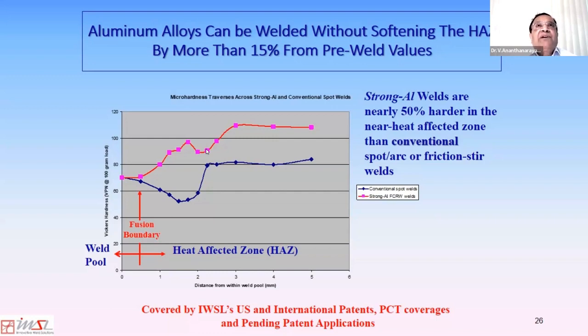And then I would do some cross sections to see how the welding process has progressed at the weld interface, and whether it has pushed out all the dirt and all the asperities in the weld interface effectively out of the intended weld joint. If it was for some cyclic loading service, I would subject it to some cyclic loading tests as well.